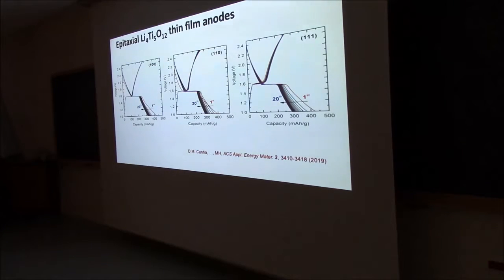And then we started to measure them against a liquid electrolyte, and you can see that from the first charge you have a higher capacity, but that's when all these reactions are happening at the interface, so where I said, okay, against a liquid electrolyte, these solid electrolyte interfaces form all these strange phases, they become constant. That's where you go from here to a situation where it's very constant during your cycling. But all three of them work very well.